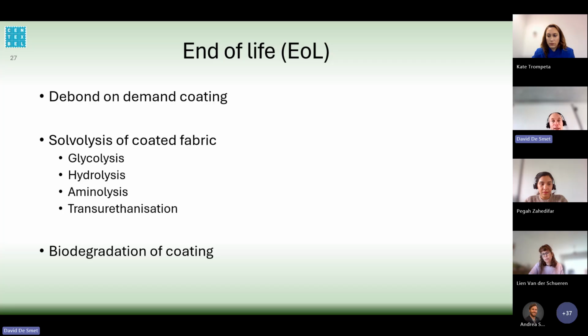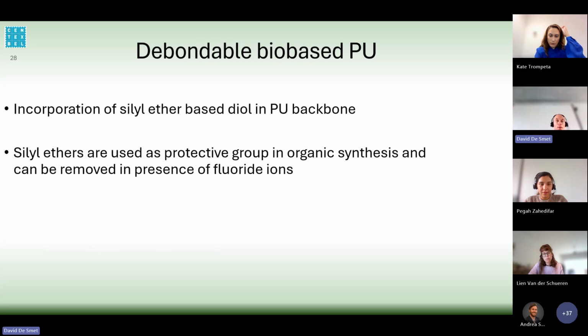And then the third way of end of life we are looking at in CENTEXBEL is biodegradation of the PU coating. So first of all, I'm just going to introduce a debondable bio-based polyurethane. There we are looking into incorporating degradable units into the PU backbone, so chemical degradable units, and therefore we are looking at silyl ether groups which can be incorporated into the backbone.